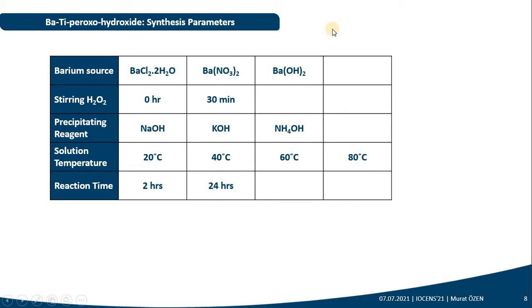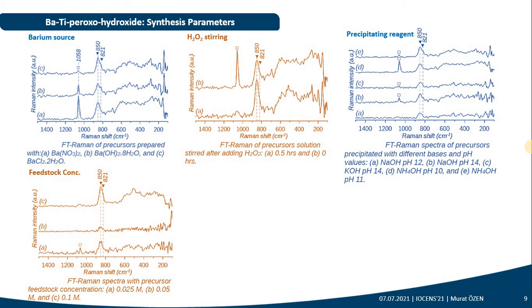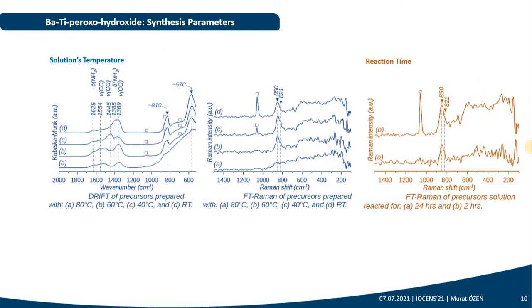So the aim of this work was actually to analyze and to study the nature of this precursor material. For this, various synthesis parameters were studied, such as the barium source, stirring of the peroxide solution, the nature of the precipitating reagents such as sodium hydroxide, potassium hydroxide, ammonium hydroxide. The temperature of the solution was also varied between 20 degrees Celsius and 80 degrees Celsius, and the reaction time of the solution was also varied between 2 and 24 hours. Some results of these synthesis parameters are shown here. These are Raman and infrared results, but XRD and elemental analysis results were also performed.